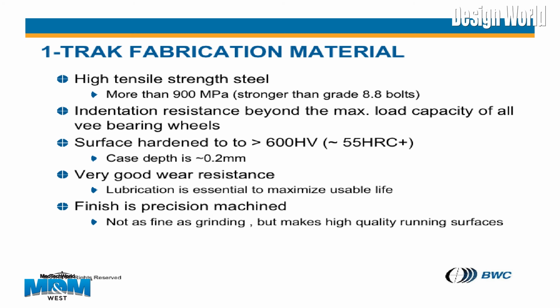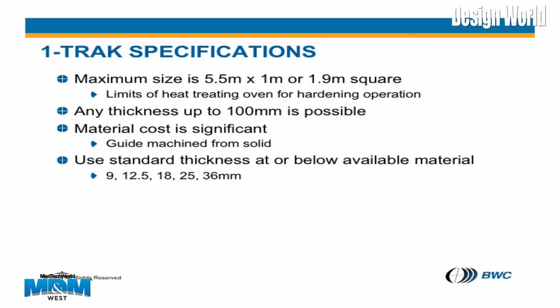We use high-strength steel, which can be higher than 900 megapascals, which is stronger than a grade 8.8 bolt. We have indentation resistance beyond the maximum load capacity of all V bearings, so the track will not dent. And with surface hardnesses, we do the case depth up to 0.2 millimeters at just about 55 Rockwell C. It's very wear resistant, and with lubrication you get very good service life.